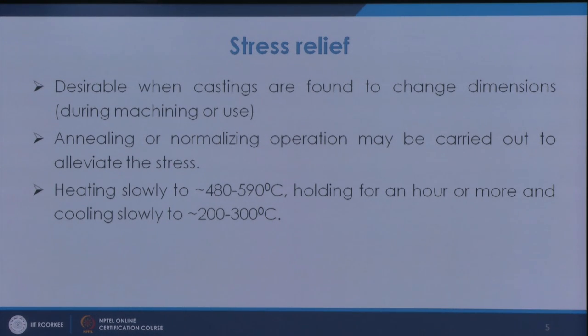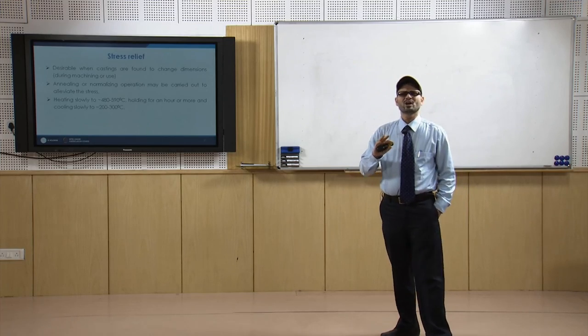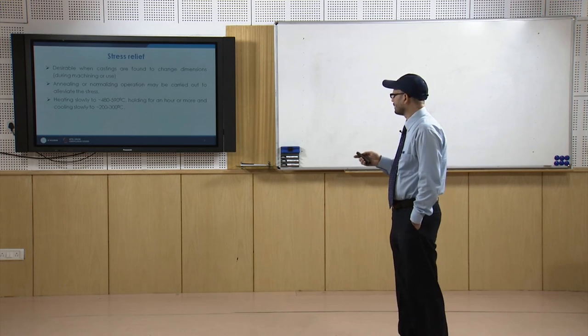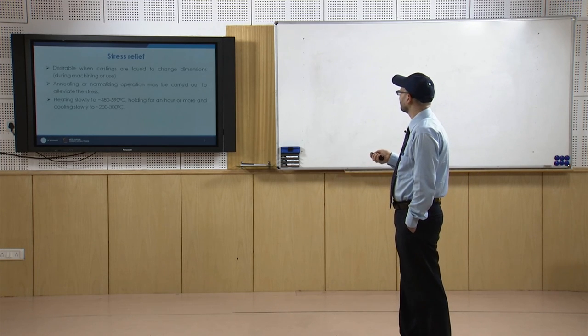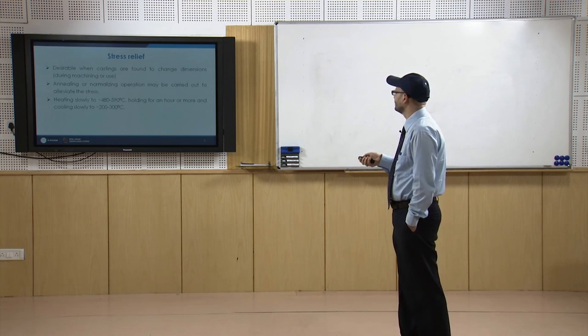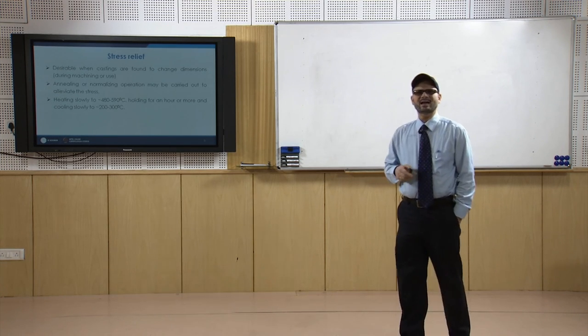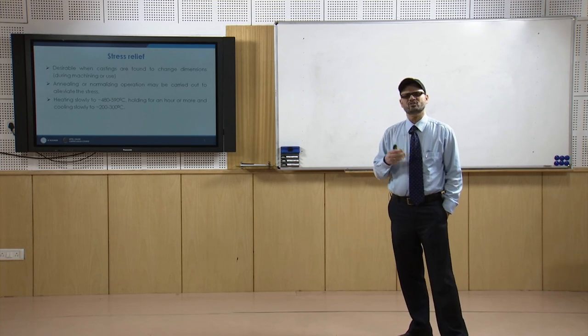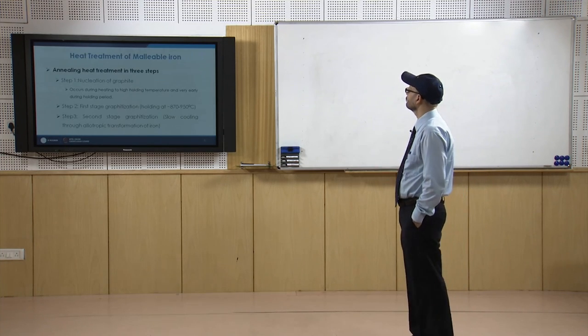For that we heat slowly to 480 to 590 degrees centigrade, hold for an hour or more, and then cool slowly to 200 to 300 degrees centigrade. This way also you try to alleviate the stress. So either you go for normalizing or annealing, or you may use this range of heating and then further cooling. That basically relieves the stresses.